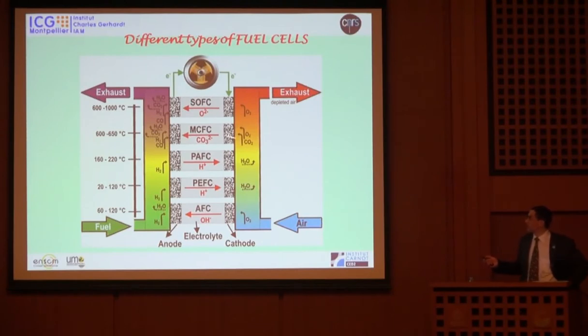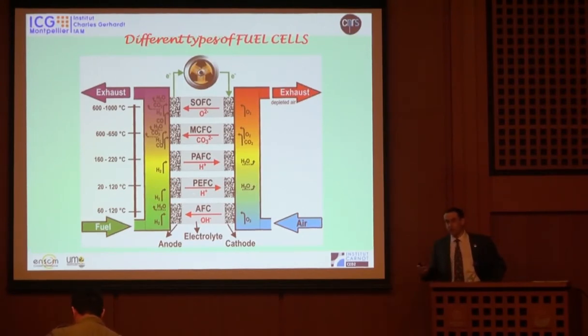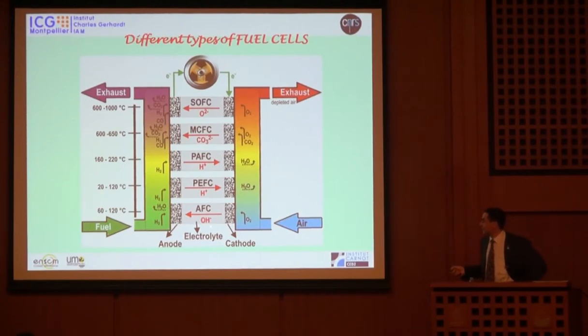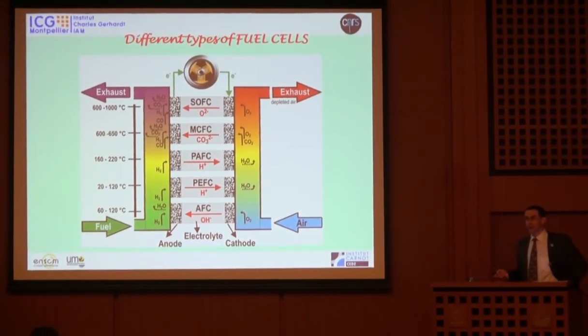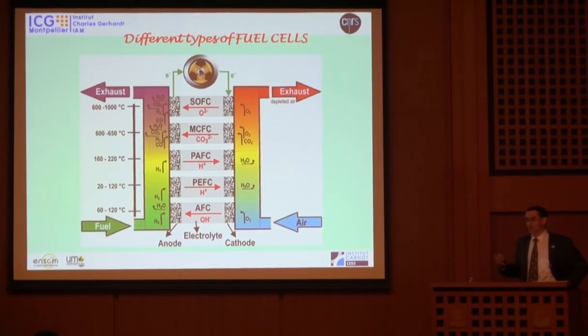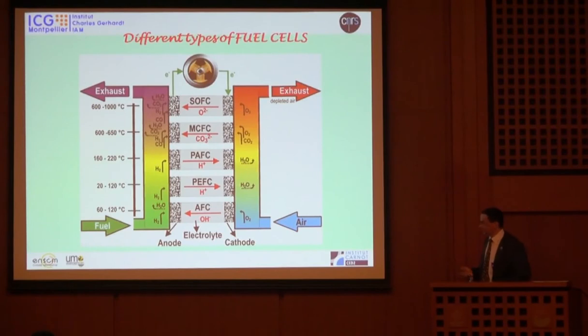Molten carbonate fuel cell, we have carbonate as electrolyte, phosphoric acid with, of course, I will come back here, we have tried to find out how to branch some phosphoric acid on a polymer. And you see that we are lowering the temperature in these conditions. Polymer electrolyte fuel cell membrane in which we try to have some sulfonic acid group which are able to transfer the protons. And then alkaline fuel cell in which you need another source of electrolyte, which is usually potassium hydroxide or sodium hydroxide. But in this condition, you can understand that the membrane, which is in a sandwich between both electrodes, has to withstand these conditions of electrolytes.